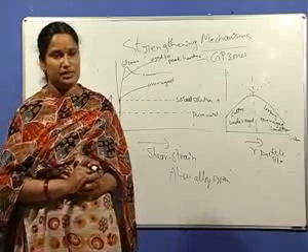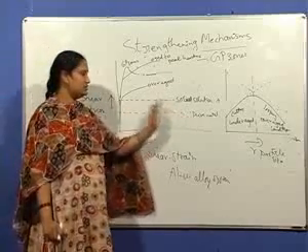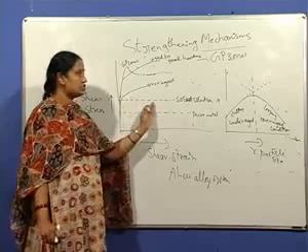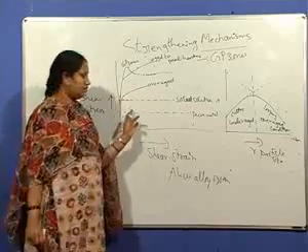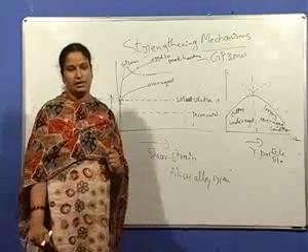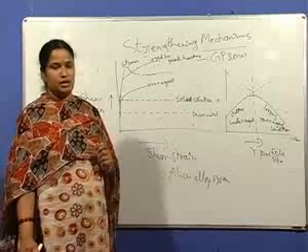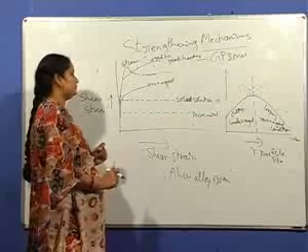These are the stress strain curves for these various stages. This is for the case of pure metal, which has some strength, and for solid solution, the strength is higher than that of the pure metal because of solid solution strengthening, the lattice strains of the solute atoms and their dislocation interaction.